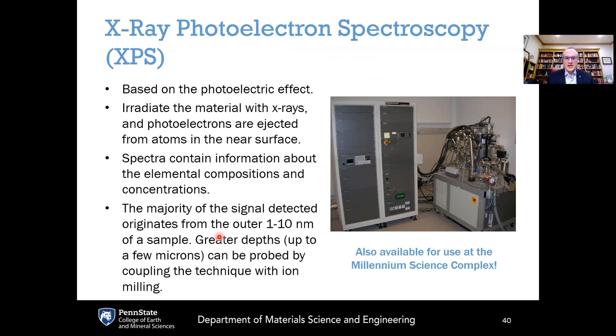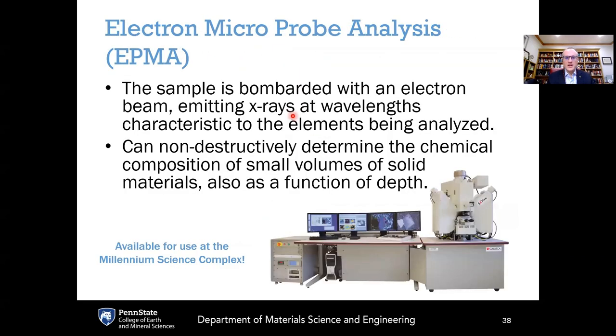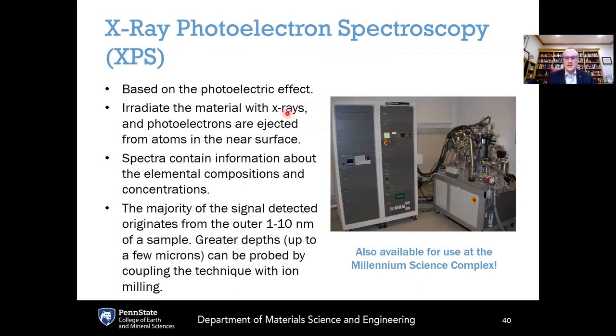One final technique here is X-ray photoelectron spectroscopy, or XPS. This is based on the photoelectric effect. And in this case, we're bombarding the sample with X-rays. So with SIMS, we were bombarding the sample with ions. With EPMA, it was with electrons. And with XPS, we're bombarding it with X-rays. And what we are ejecting from the sample are electrons. These are called photoelectrons because they were released by hitting it with radiation. These photoelectrons are ejected from atoms near the surface, and then their spectrum is analyzed to get information about the elements that are present and in what concentrations.